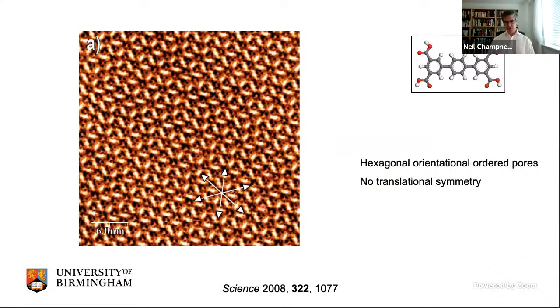So I want people to just look at this for a moment. Each of the bright features is an individual molecule. And if you pick any molecule you like, I don't care which one, and go in any direction you like, and just go from this molecule to this molecule to this molecule, just move in a straight line, you'll see that there is no translational symmetry. So this doesn't actually form a regular structure. This forms this really quite bizarre system which has no translational symmetry.